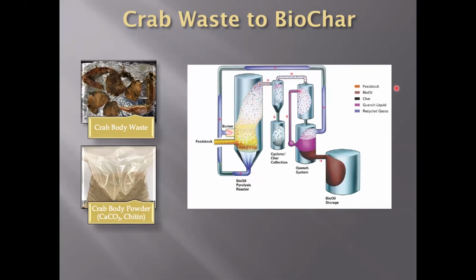And so I'm not going to get into too much detail around the process of pyrolysis. There's 2 major types of pyrolysis, slow and fast. In our lab, our focus is largely on slow pyrolysis, but we have the ability to do both. And what pyrolysis is basically, you take your biomass feedstock that's dried, feed it into a burner. The burner can be powered with electric heat, or it could be through utilizing the combustible gases that are produced and burned to provide the heat. And the larger material components or larger compounds or particles are collected in some sort of collection matter, whether it's a cyclone or a filtration unit, as what is considered the biochar, the char collection part of the pyrolysis process. The smaller molecules will either be condensed to form the bio-oil and water phase and collected as bio-oil.